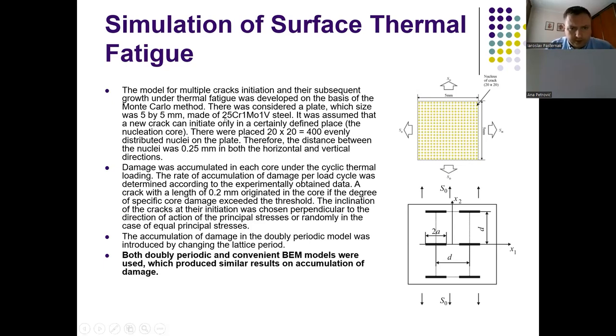That was the first model where cracks initiated and grow in such a way. Another model was made based on that doubly periodic representation. We consider some cracks where the periodicity, the period, is assumed to be the same in x1 and x2 directions. That period also defines the cracks density, how many cracks are distributed in some area.